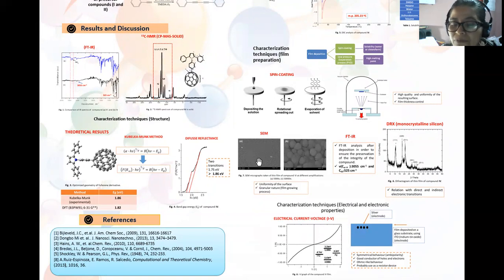The study of morphology and uniformity was achieved using the same technique. The thin film was deposited on silicon wafers. The surface is uniform, with homogeneous distribution over the base. There are no holes or particle clusters. This morphology is the result of the film growing process, which initially reacts to high temperatures, with subsequent gradual lowering of these values, favoring the formation of grains on the surface. These attributes strongly suggest good electronic characteristics.